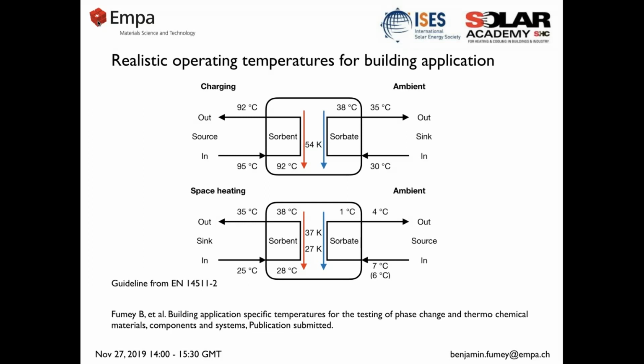Without going much further into these temperatures, here you see, as Wim had pointed out, we need charging temperatures, we need ambient temperatures for a heat sink, we need source temperatures in discharging, and in this case we need a certain space heating temperature. With defining these temperatures, it is possible to evaluate from the milligram level materials to the system, the performance of material in component and in system. So this is one of the very important initial common grounds that we have defined now for building applications.